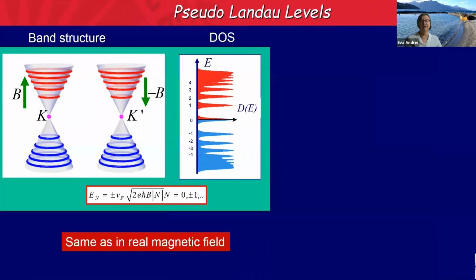The band structure in the presence of a regular magnetic field is the same as in the presence of the pseudomagnetic field. You have these Landau levels with the Landau level at zero energy here. However, the only difference is that whereas in a real magnetic field that breaks time reversal symmetry, the sign of B is the same in both valleys, here it has opposite signs. However, the density of states really doesn't care about the sign of your field, so it's going to be exactly the same as if you had a regular magnetic field, and you're going to have the regular sequence of Landau levels, which goes like the square root of the pseudomagnetic field this time and the Landau level index.